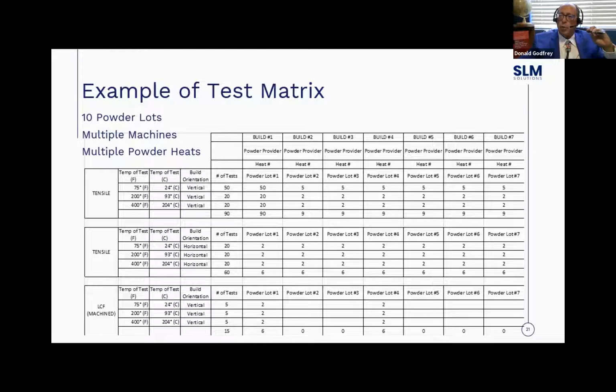It's always great to have multiple machines, and then you're going to have a discussion with your material science people and your structures people and your engineering group. How do you want to test? Now, to get MMPDS, you need to do 300 specimens. So let's say you do 300 tensile specimens. There is a debate, and it hasn't been decided, should those 300 specimens be at the same temperature? But you're going to do room temperature, which is 75 degrees F. And what I've typically done over the years is I jump up in 200 degree increments.